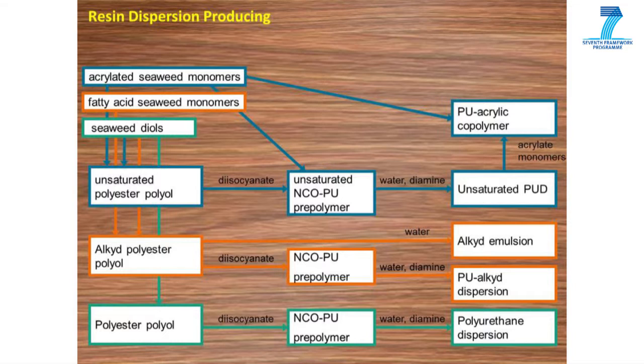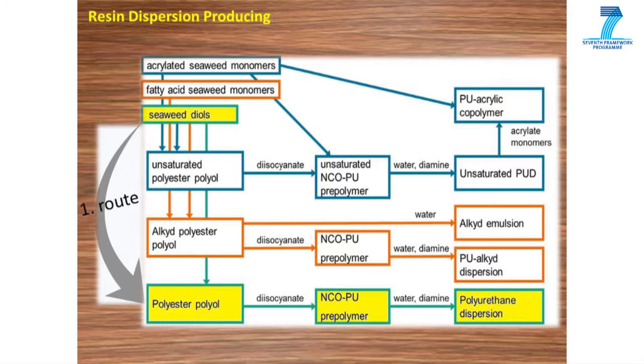Seaweed monomers can be taken from the saccharide or the oleo part of seaweed components. The first route shown in figure starts with seaweed diols to synthesize a first intermediate polymer called polyester polyol. After conversion with diisocyanate, we will obtain the second intermediate polymer called NCO-terminated polyurethane prepolymer, which can be dispersed in water to get a waterborne coating resin.